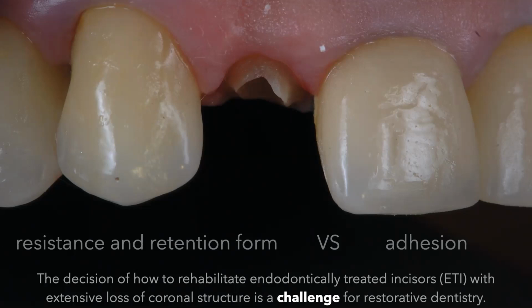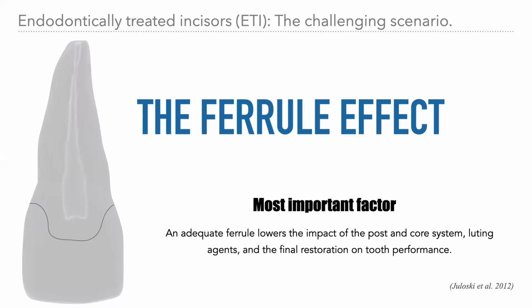So the decision of how to rehabilitate endodontically treated incisors with extensive loss of coronal structure is a challenge for restorative dentistry. What we know is that the ferrule effect is a general agreement. The ferrule is the most important mechanical factor for the strength of endodontically treated incisors. The presence of an adequate ferrule decreases the impact of the post and core systems, the luting agents, and the final restoration on the performance of endodontically treated teeth. Also, teeth with ferrule have a tendency to fail in a more favorable mode.